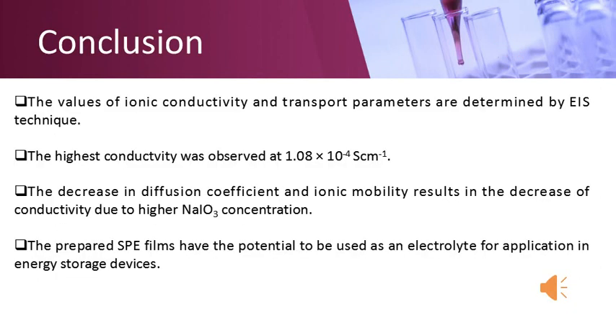So, in conclusion, cornstarch sodium iodate solid polymer electrolyte has been prepared using a solution casting technique, and the ionic conductivity and conduction mechanism of the SPE films were characterized using electrical impedance spectroscopy, which is EIS. The ionic conductivity of the SPE films increases to the optimum value, which is 1.08 × 10^-4 Siemens, with the addition of 3 weight% of sodium iodate. The transport properties of the SPE films, such as mobility, number of mobile ions, and diffusion coefficient, have been calculated using the EIS method too.